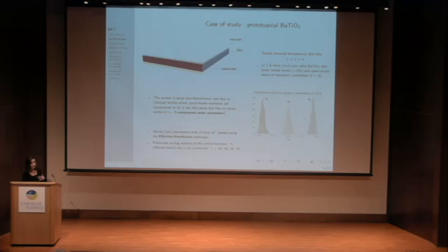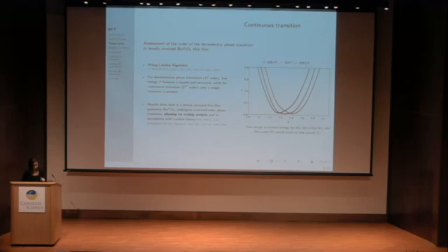So we have performed Monte Carlo simulations as well as molecular dynamics simulations using the effective Hamiltonian scheme. And we have considered several lateral sizes of our system. So preliminarily, we had to assess the order of the phase transition leading to the long-range ferroelectric order. And for that, we have performed some Wang-Landau algorithm-based simulations that enable us to assess the structure of the free energy with respect to the internal energy.